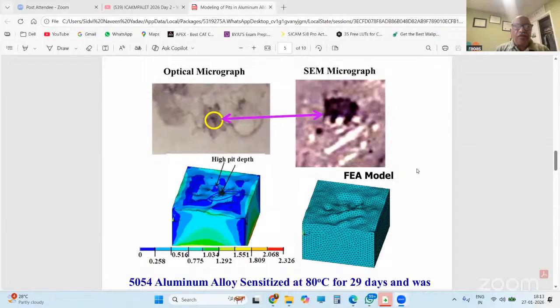Okay, here is the case. We took one of those pictures of corroded pits. After 29 days, the small spot became big. On the left top is an optical micrograph, and on the right is a scanning electron microscopy micrograph. We took that, digitized it, transformed it, and created a stress field of that image as a FEA model.